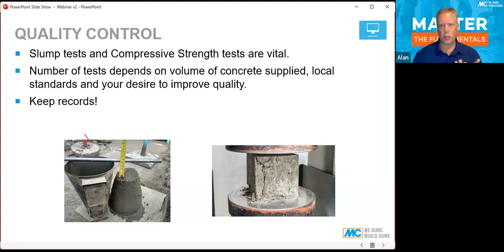The second one, which concrete is mainly defined by, would be the compressive strength. We make samples for maybe 24-hour, 7-day, 28-day, and we make sure it meets the project specification. It's important to keep good records. Regular testing can help us to identify any deviations that can mean there's an issue on the plant. Tools like CUSUM can help us to analyze the results and look for trends that can help us to improve the quality of our plant also.